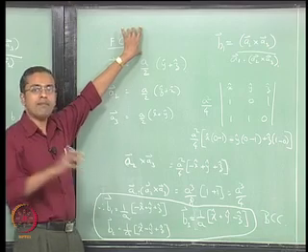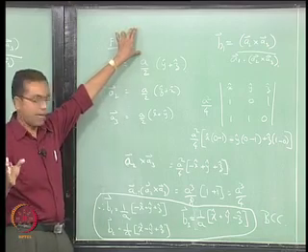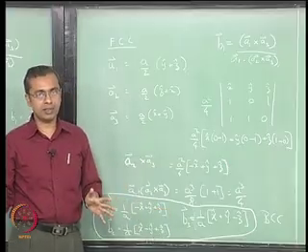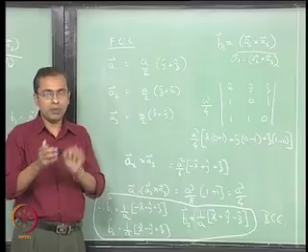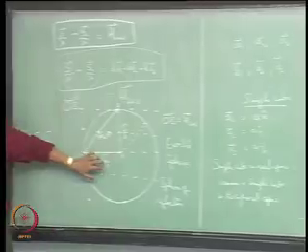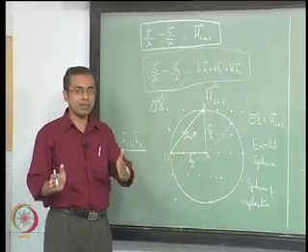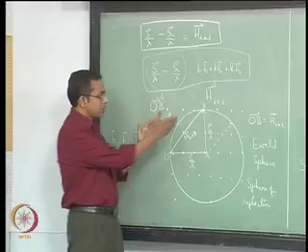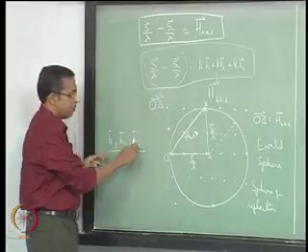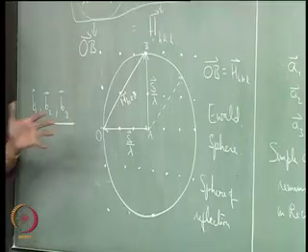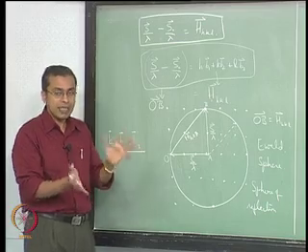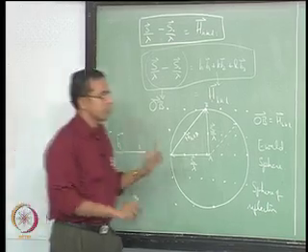This same material, when represented in reciprocal space, will have a geometry that is similar to that of a body centered cubic material. So the layout of the points, when you lay out those points, the real material being face centered cubic, when you plot these reciprocal lattice points B1, B2 and B3, will have a layout that looks very similar to, in fact identical to, a body centered cubic layout. Okay. So that is the thing.